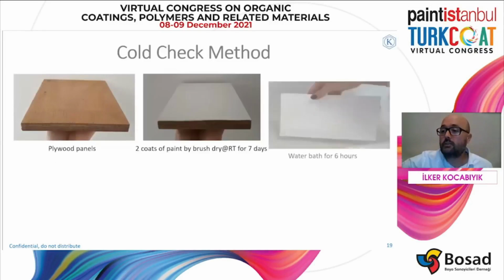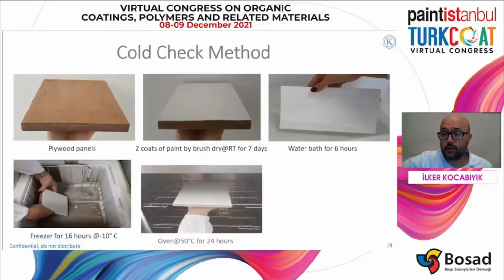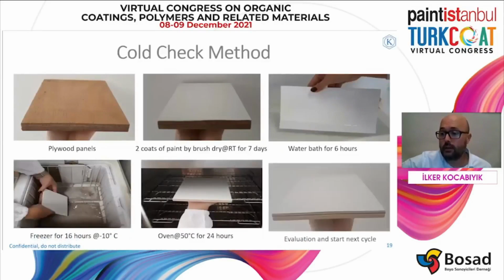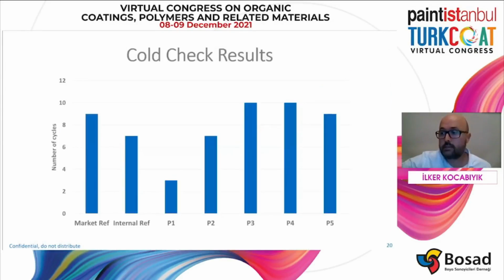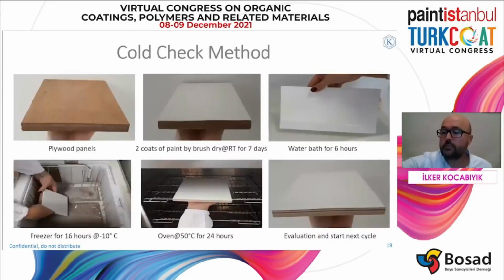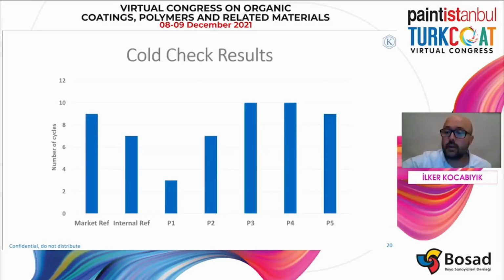Cold check resistance of paints is tested with the following procedure. Birch plywood panels are coated with 2 layers by brush and dried at room temperature for 7 days. Then the following steps are carried out for each cycle: 6 hours water bath, 16 hours freezer at minus 10 degrees Celsius, followed by a 50-degree oven for 24 hours. After each cycle, panels are evaluated and cracks are carefully noted.